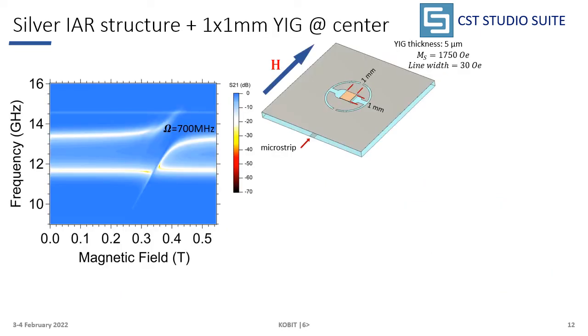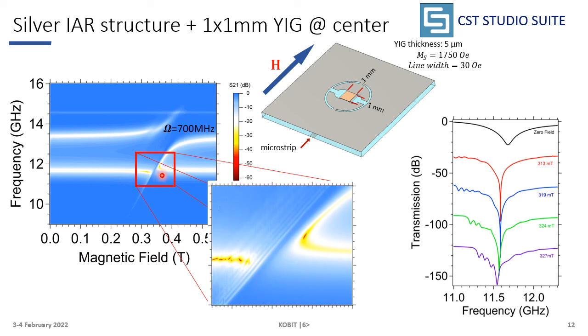In coupling simulation studies of the silver inverse anapole resonator structure with thin film, we used a YIG thin film 1 by 1 millimeter in width and 5 micrometer in thickness, placed at the center of the resonator. The line width of the YIG film was defined slightly larger than the literature value to decrease the computation time. As seen on the transmission coefficient map, in this configuration we obtained strong coherent coupling between the second resonant mode and the magnonic modes, and the formation of dissipative coupling with the first mode of the resonator was also obtained.